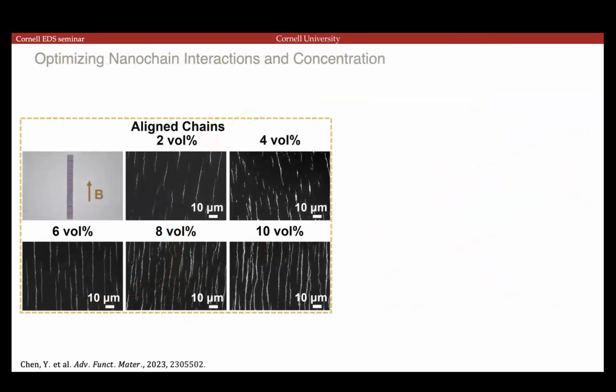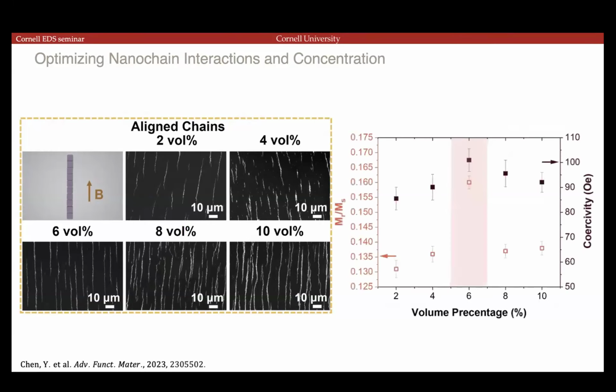Nevertheless, my student tried to optimize this and make it into an actuator just to show its performance. She measured the net magnetization of the composite as you vary the concentration of these. If you make them really high in concentration and really packed in, they're going to couple magnetically to each other and effectively reduce the net magnetization, just like they would in a multi-domain material. But if they're low concentration, then you have low magnetization simply because there's a lower amount of magnetic content.